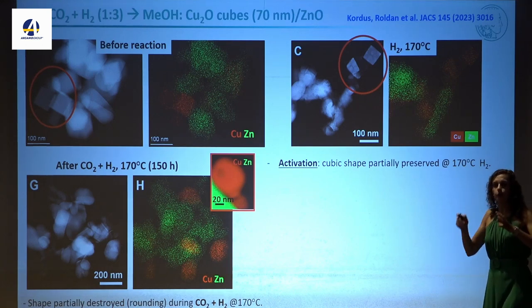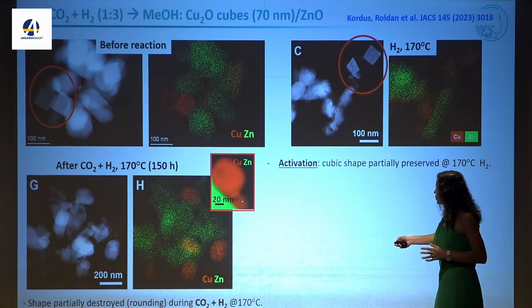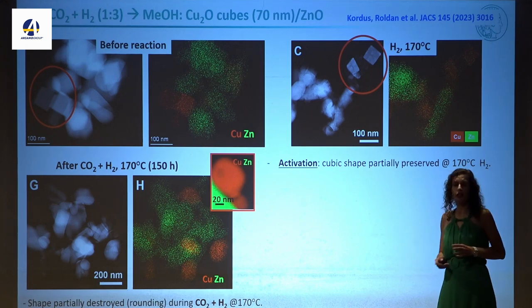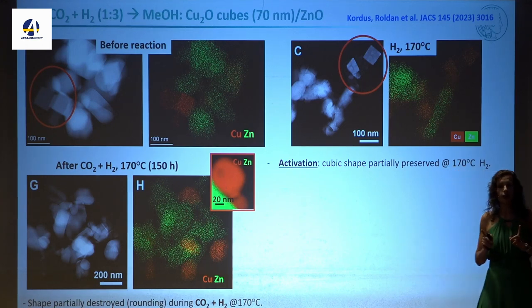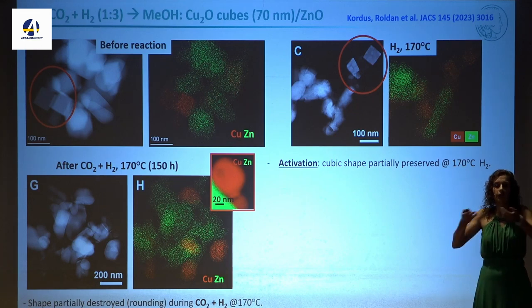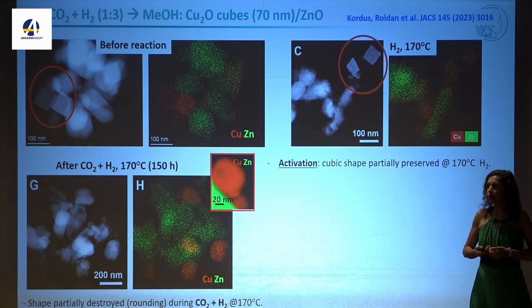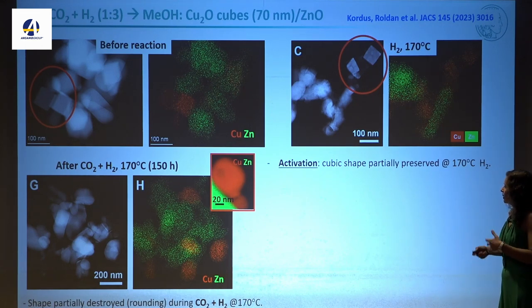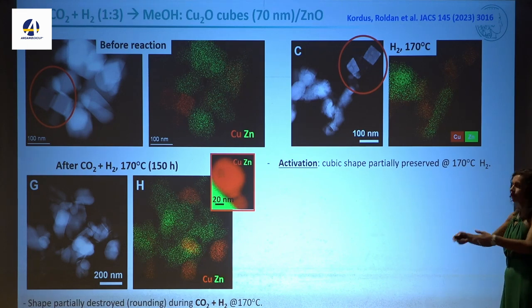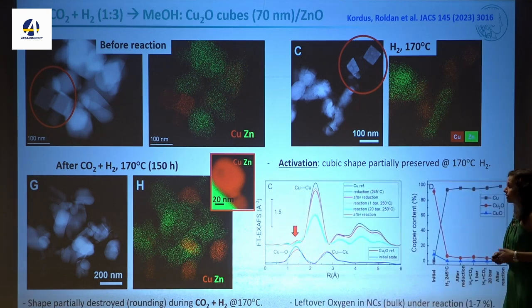But if you start with this pre-catalyst shape, you already ensure that you have a large surface contact area with the support. I think this is very smart for this system because the system likes to encapsulate the copper. So if you make something like this, maybe you get higher active interfacial area. So that was our hypothesis, even though we knew that the shape will be having changes. So we can follow this.